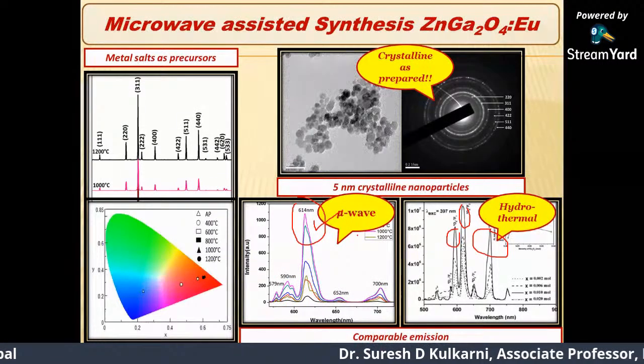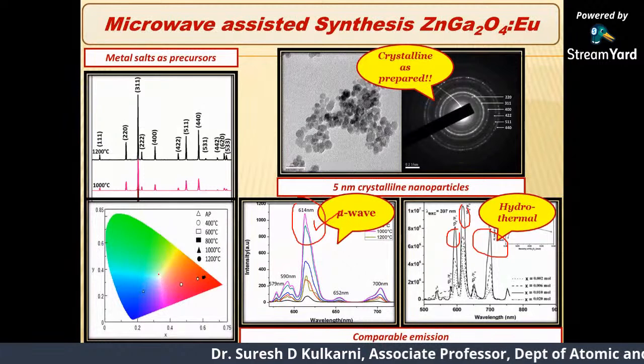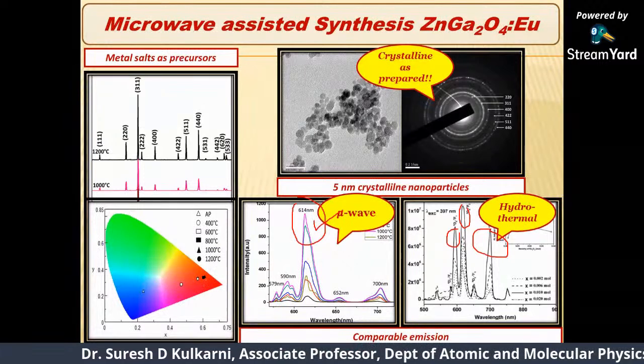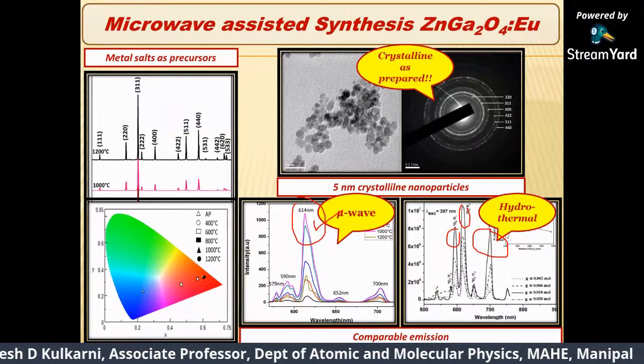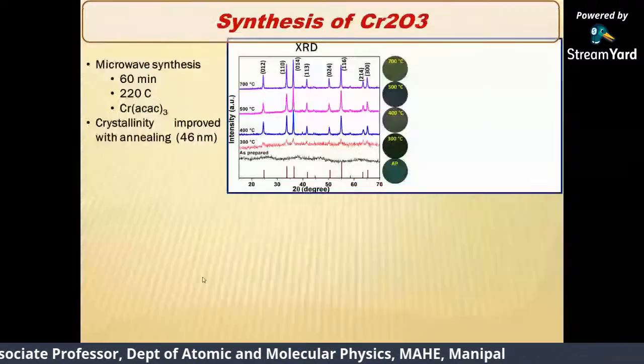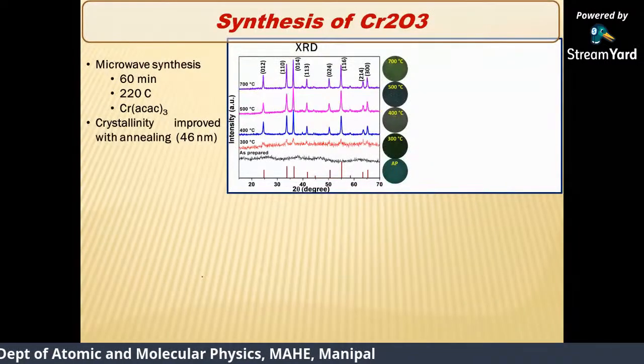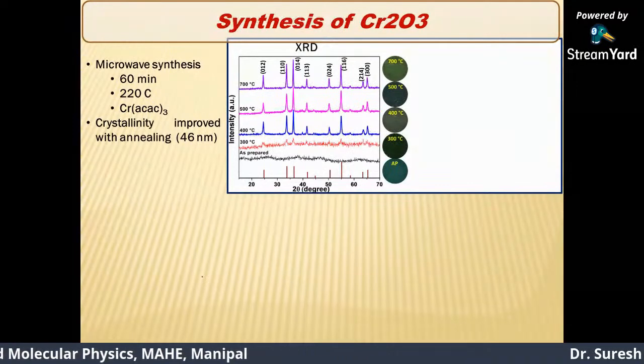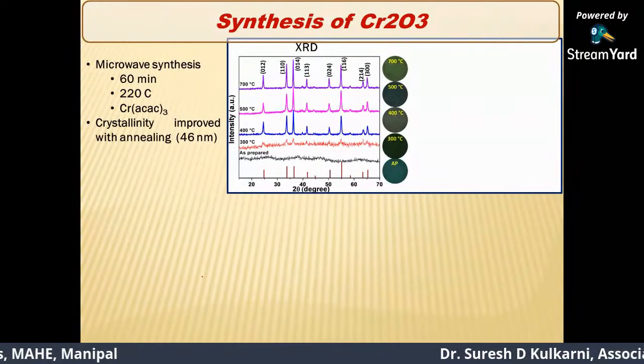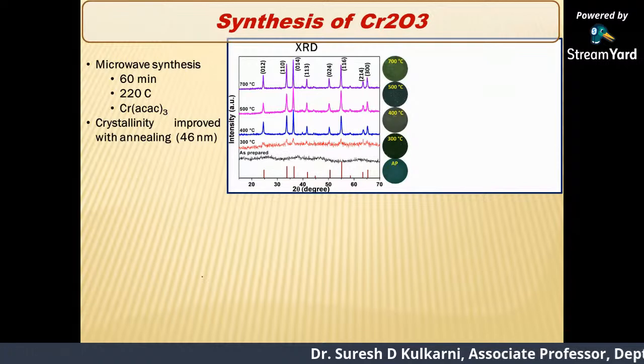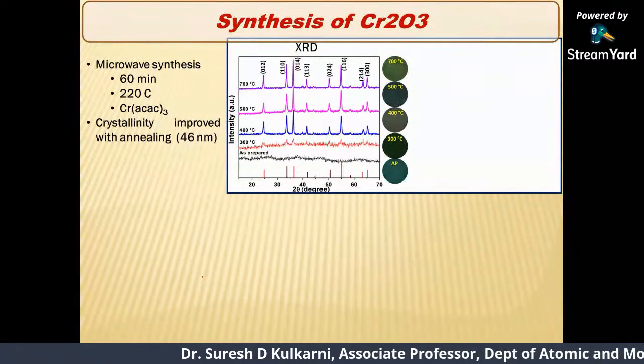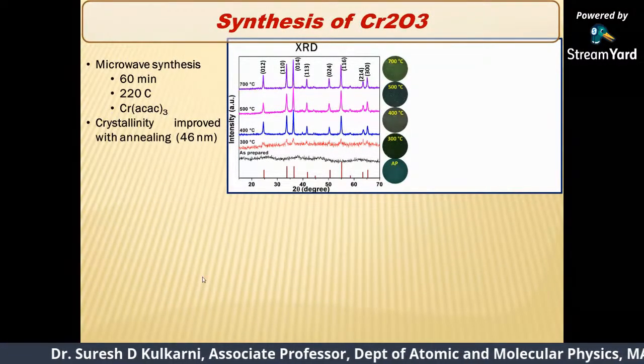And the quality of emission is shown by what you see in the picture. So it is giving you good quality red light, and that is very close to the standards of the television industry. Similarly, we have prepared a chromium oxide using microwaves within 60 minutes, starting from a metal organic complex.